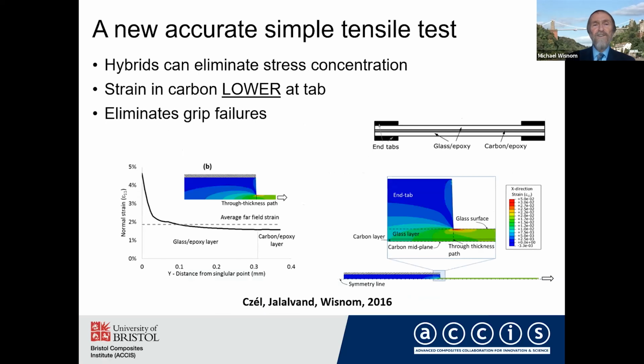Recently, we've done some work on a new test method, which I think is really very, very promising, whereby we use hybrid specimens. So this came really as a byproduct of a lot of work we were doing on looking at hybrid composites. And in this case here, we've got a specimen with carbon fiber epoxy and glass fiber epoxy on the outside. So it might look like a sort of an in situ tab, but there's more to it than that, really, because this is not just providing a tab, it actually eliminates the stress concentration altogether.